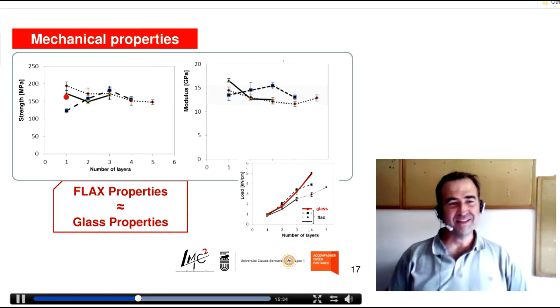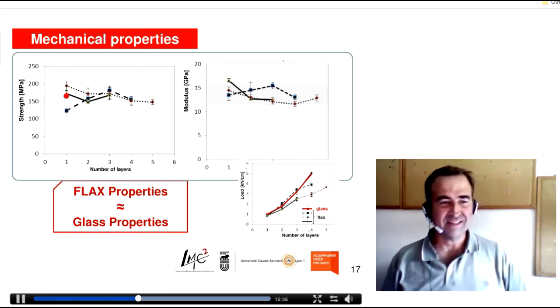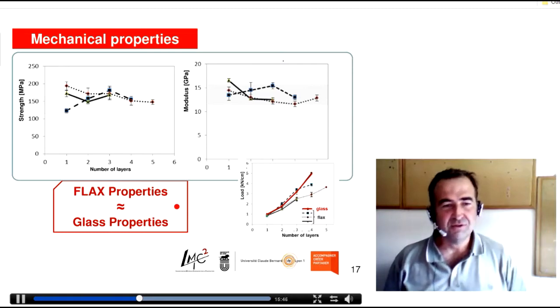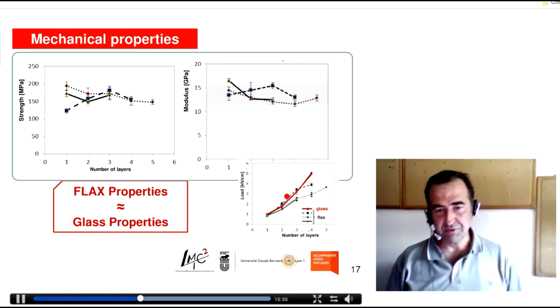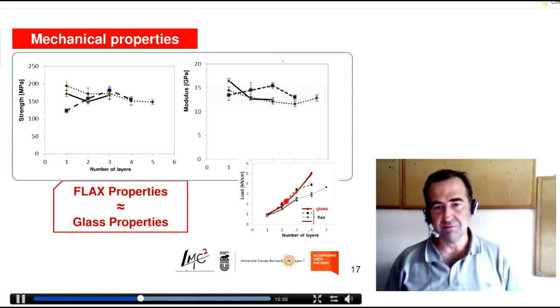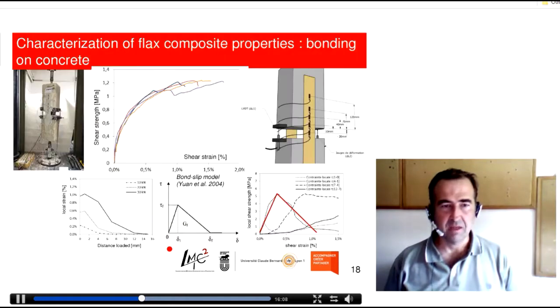What we observed is that we had tensile strength nearby 150 megapascal and Young's modulus about 15 gigapascal. So in first conclusion, what we can observe is that flax fiber properties may be more or less comparable to glass fibers. Here we have very light glass fibers, about 200 grams per square meter, compared to the flax fiber composite we have in our study.